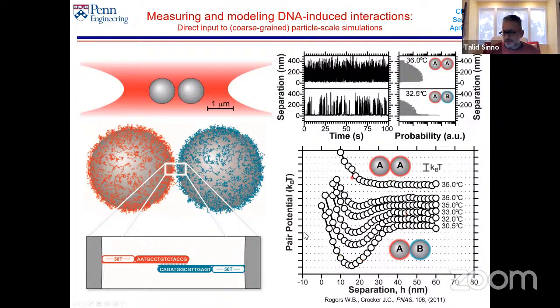So these are examples of the pair potential between a pair of these particles, and they're color coded according to the DNA sequence that is on each particle. Red particles have this sticky bit, and blue particles have this. What's interesting is that this is not self-complementary. So if you brought another blue particle and tried to put it up here, it wouldn't match with this one. So it's selective. Red always meets with blue, but blue doesn't bind to blue and red doesn't bind to red. If we label red and blue as A and B, there are attractive interactions between A and B, and they would look like this, but there's no attraction between A and A, and you'd only see the repulsive part, okay?